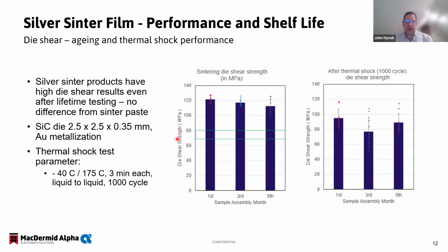Typically in a non-aged sample, so no thermal conditioning done to the substrate, we look for a die shear strength of give or take 70 megapascals. And you can see here, even after thermal shock, most of the dies still maintain that target value. The thermal shock parameter that we used on this test was -40 to 175 C, liquid to liquid at 1,000 cycles. So this was a very, very accelerated, very harsh test just to prove that the material still holds up after aging.